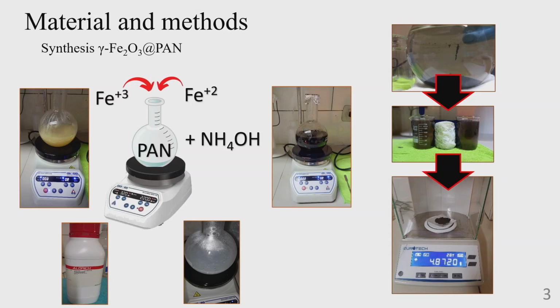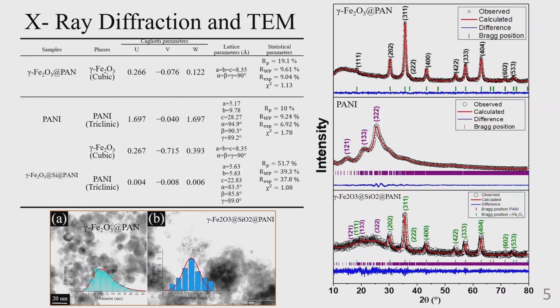So, as we have the samples, for the X-ray diffraction, in the diffraction of the end results we have in the figure here the diffraction profile of the maghemite with polyacrylonitrile sample, which only displays peaks of the maghemite phase. Here one must mention that the polyacrylonitrile polymer has no long-range crystalline order because it's semi-crystalline, and it's overlapped by the maghemite. Consequently, an X-ray amorphous feature is seen in the spectrum, but the X-ray diffraction shows the crystalline contribution of the maghemite phase.